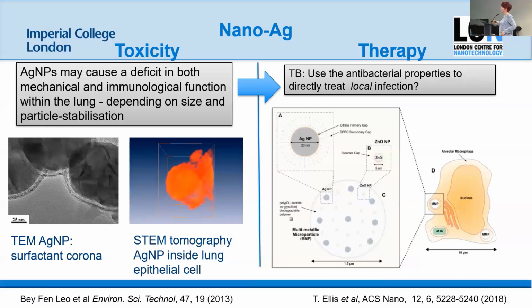And silver sulfide, it turns out the solubility product of silver sulfide is 10 to the minus 52. Right? So it just doesn't want to go anywhere. Silver meets sulfide, it's dropping out. What this does when we do this experiment in animal studies, it causes a cascade of enzyme upregulation because you take sulfur out of a system and then you get this response where the body creates more H2S locally. Okay, but the good news is this trapping of the silver ions by the sulfur is somewhat of a detoxifying mechanism, right? Because it's the free ions that normally cause the toxicity.